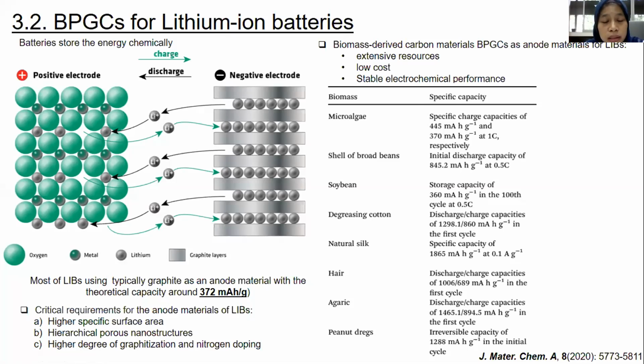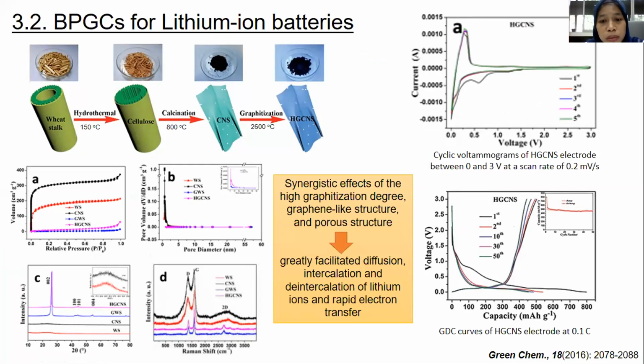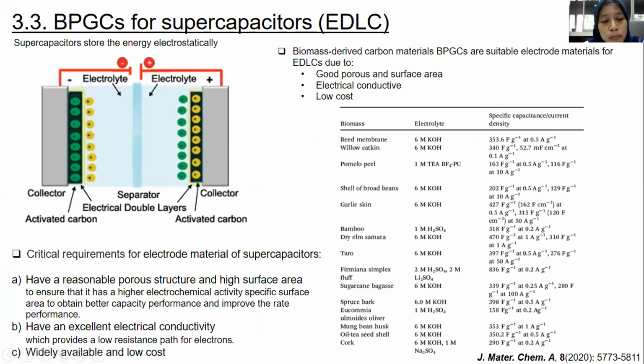Okay, this is a paper about the biomass application in the battery. From the wheat stalk with the calcination and graphitization method at higher temperature, we can see that it has a good performance as an anode of lithium battery because of the synergistic effect of the high graphitization degree, graphene-like structure and porous structure, which greatly facilitates diffusion, intercalation, and deintercalation of lithium-ion and rapid electron transfer.